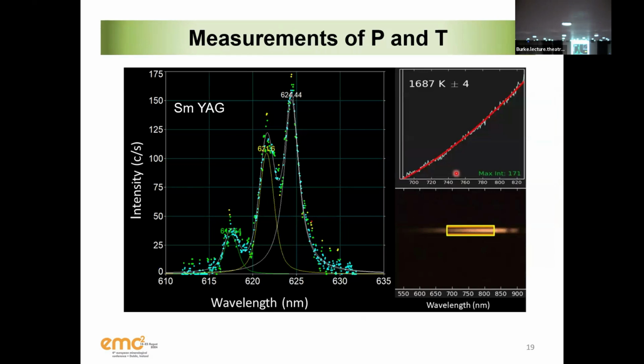At the same time, we do Brillouin, and from the same pinhole we measure temperature, so the emissivity of the sample, so we are sure that we are measuring the temperature where we are collecting the Brillouin scattering. And then we measure pressure, because we discovered after a while that the pressure doesn't change so much, but it does change. So if I want to get data as accurate as possible, I need to know what the pressure is at temperature.